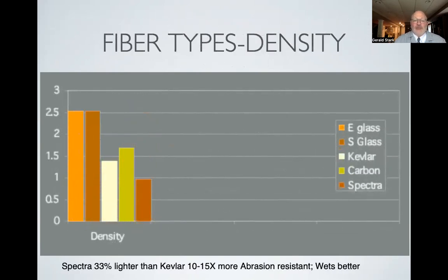Spectra is about 33% lighter than Kevlar and 10 to 15 times more abrasion resistant. So that's why you see Spectra, or Dyneema, the trade name, used in some of the gardening gloves. Dyneema also wets better. So sometimes we use Dyneema more than Kevlar at the present time.